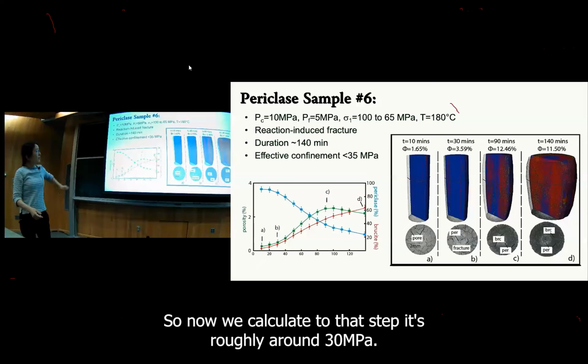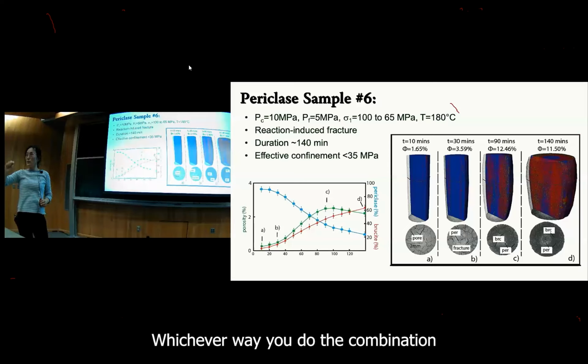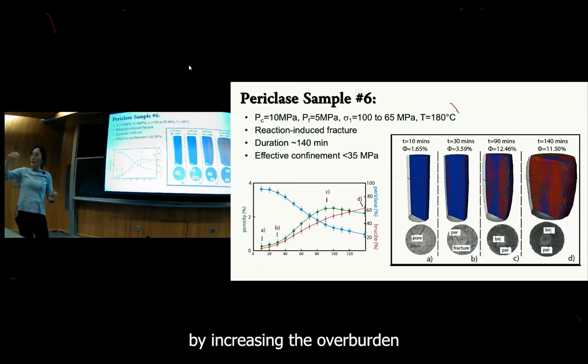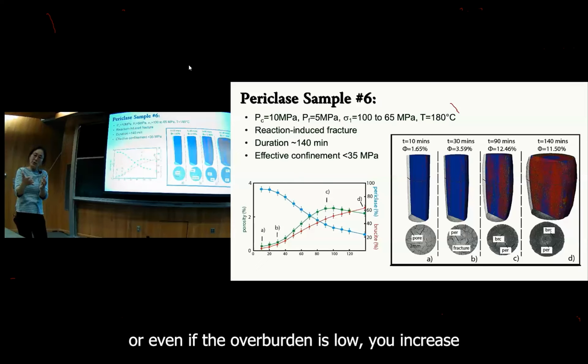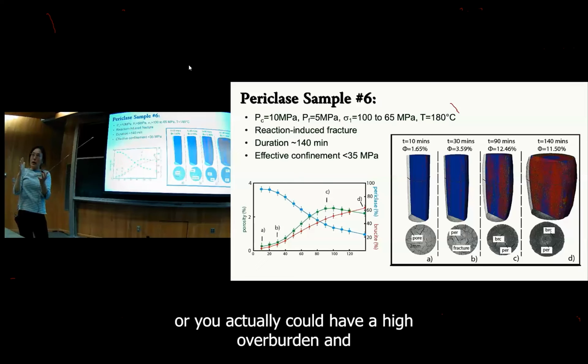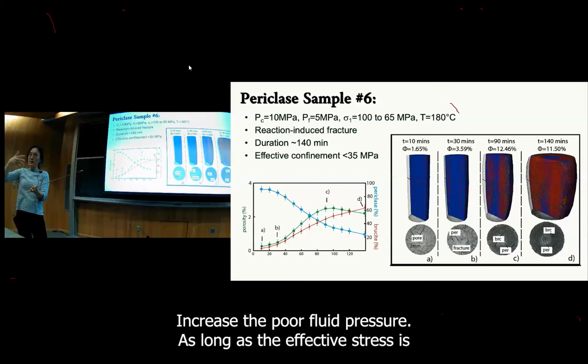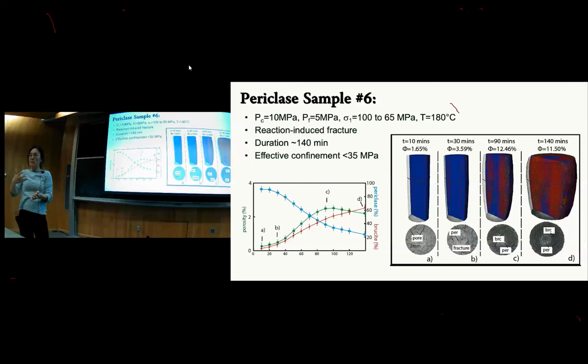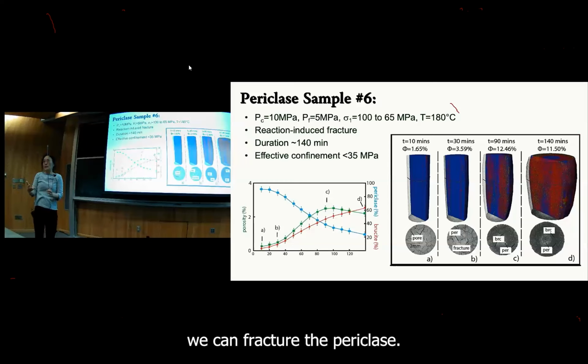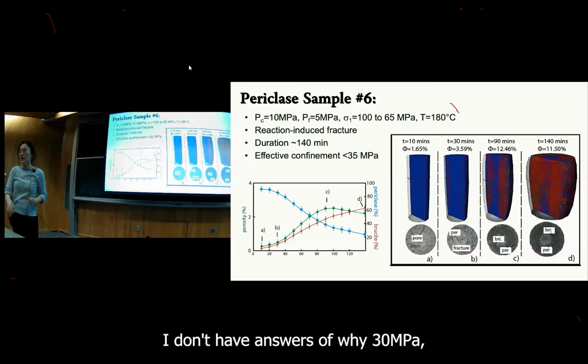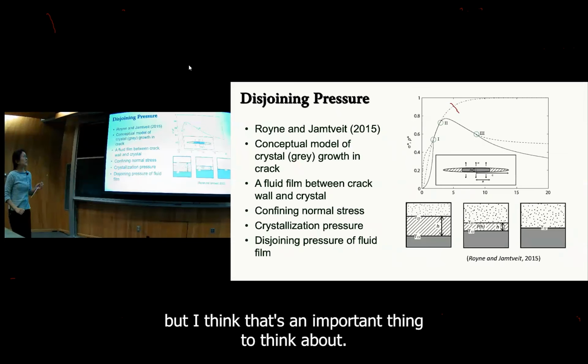All right. So now we calculate that it's roughly around 30 MPa. Whichever way you do the combination, by increasing the overburden, or even if your overburden is low, you increase a deviatoric stress, or you actually could have a high overburden and increase the pore fluid pressure. As long as the effective stress is below 30 MPa, we can fracture the periclase. Once you go above that, we can't. I don't have answers why 30 MPa, but I think that's an important thing to think about.